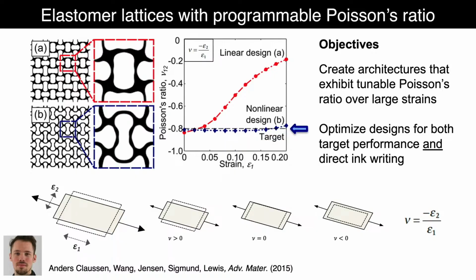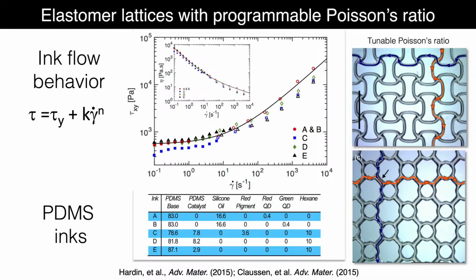And so on top of this ability to dial in systematically a specific Poisson ratio, we also wanted to make sure that whatever design was computed by their group, which is a computational group, could actually be printed. So that was the second constraint. Is it printable? Is it manufacturable? In this case, we used these elastomeric inks. These are PDMS materials that we designed to be printable. We can vary the stiffness by changing the base to catalyst ratio. We can make them colored if we need to, and we can dilute them with things like silicone oil. In this case, we just used a standard formula without.